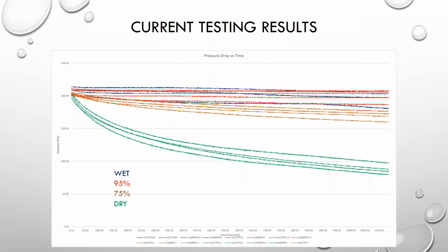This is the results of the first set we did. There's 4 specimens that were tested for each of the different moisture content between wet, 95, 75, and dry. The dry is the green, and you can see that had the greatest pressure drop. Then 75 is the brown color. Then between 95 and wet, they are sort of intermingled between here. So very little difference between them. So as the drier the specimen are, the more pressure drop we're getting.